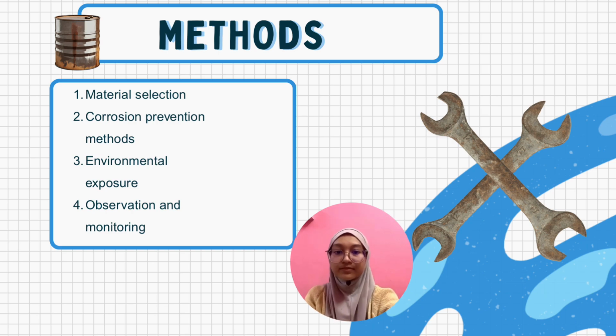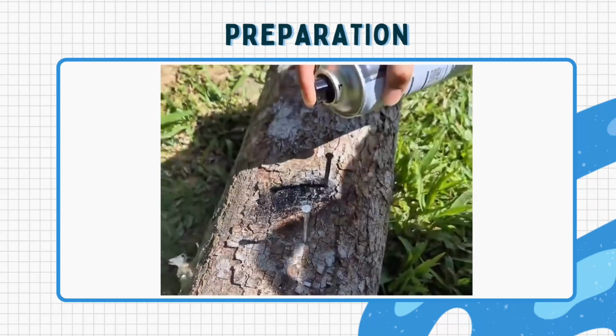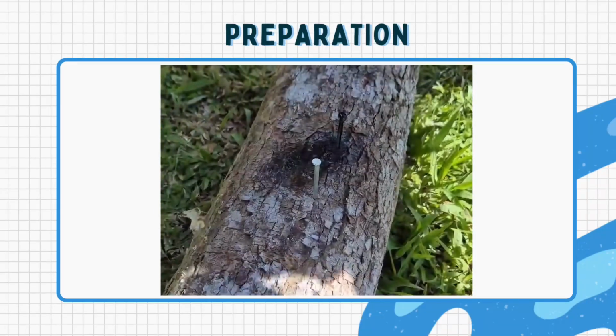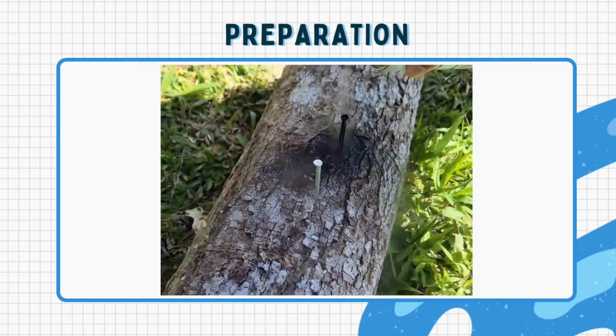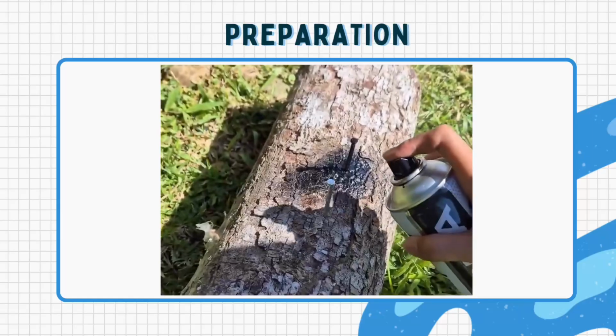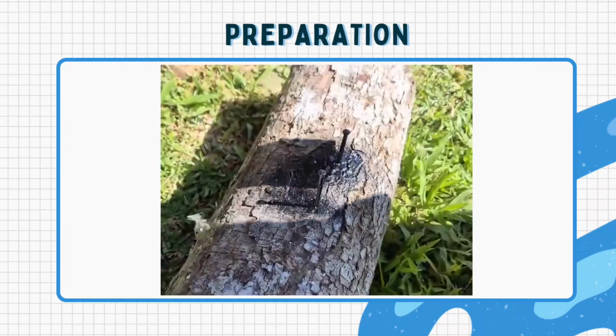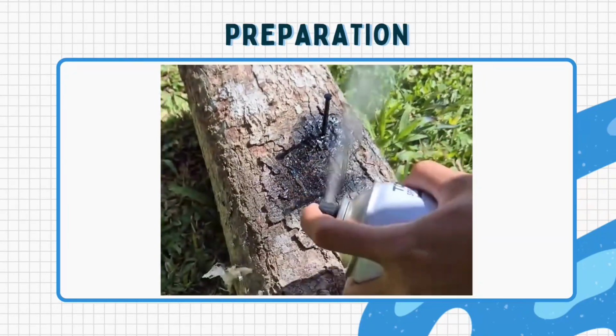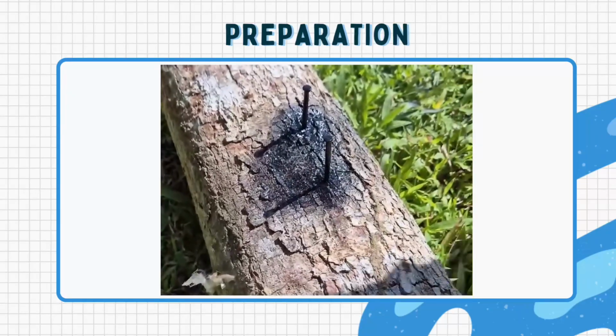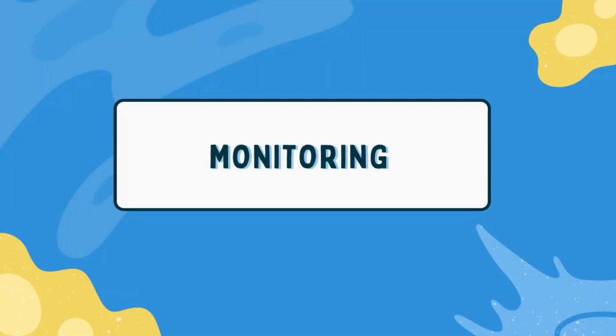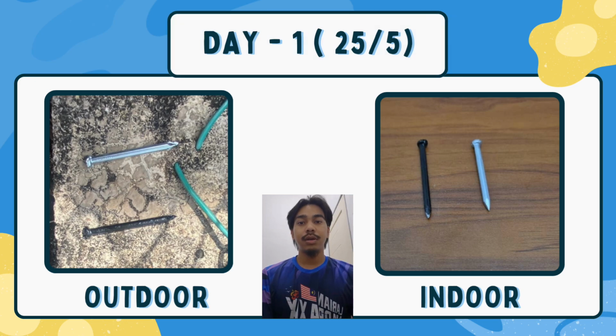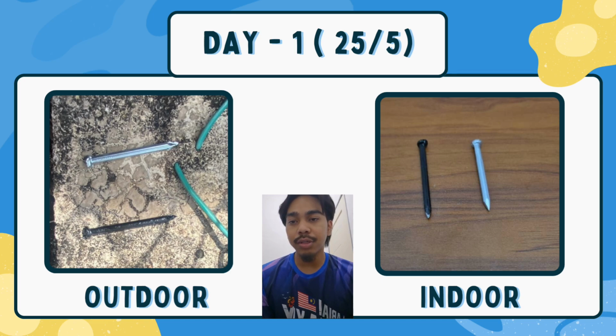The surface remained unchanged; both uncoated and coated show no sign of rust, and the spray paint coating remains intact. For outdoor exposure, the spray coating on the nails began to wear in several areas. However, for indoor samples, no visible signs of corrosion were observed. Both samples remain free from rust. The nail coated with spray shows areas where the coating had partially worn off, exposing parts of the original surface. Despite this, no visible signs of corrosion, such as reddish brown rust, were observed. Meanwhile, for indoors, the uncoated nail shows no signs of corrosion at all.